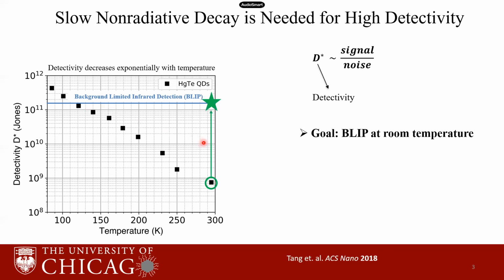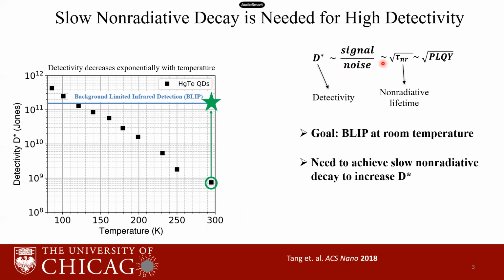So the holy grail is to achieve background limited detection near room temperature, and this is denoted by this star over here. And we are currently 2 orders of magnitude below this level. So we need some method to reduce the noise without cooling the detectors. And we can do this by slowing the non-radiative relaxation in these quantum dots. The detectivity goes as a square root of the non-radiative lifetime, which is proportional to the PL quantum yield.